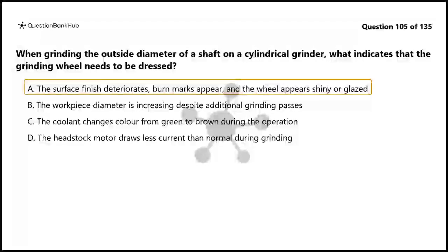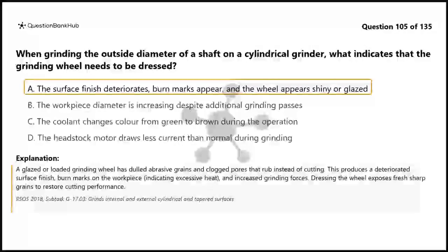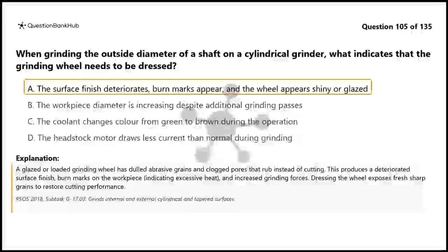The correct answer is A. A glazed or loaded grinding wheel has dulled abrasive grains and clogged pores that rub instead of cutting. This produces a deteriorated surface finish, burn marks on the workpiece, indicating excessive heat, and increased grinding forces. Dressing the wheel exposes fresh sharp grains to restore cutting performance.